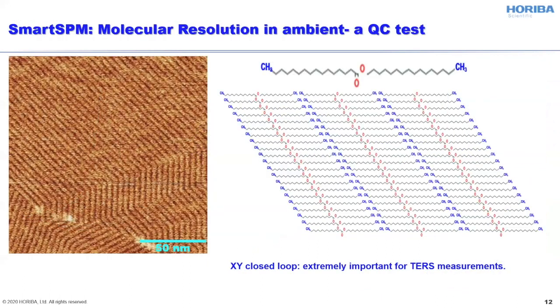I would like also to stress the importance of having the AFM with XY closed loop control. This control eliminates the creep in actuators in the piezo scanner and allows you to be exactly in the position that you want to be. And as you can see in this example, this AFM image of molecular self-assembled layers on HOPG collected with XY closed loop on shows that we can do a quite nice job even at nanoscale.